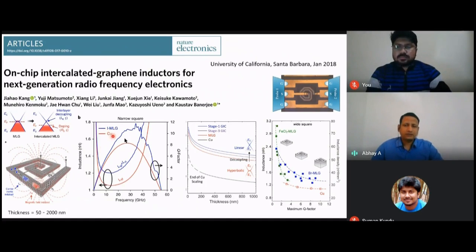They compared the performance of the inductor. This coil is an inductor, and they measured the RF performance of it. They plotted inductance as a function of frequency, and compared this graphene inductor with existing state-of-the-art copper inductors, and they noticed that the inductance is quite high. Even if the numbers look small, like 1.5 nanohenry to 1.7, 1.8 nanohenry, this is a significant improvement. And they saw the scaling of the same with thickness of graphene and copper.